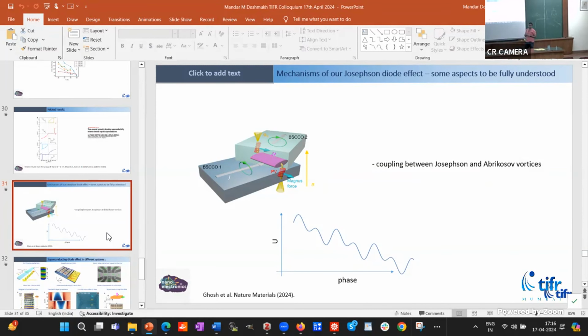Is that a point of inflection on the curve or something like that? This is a local minimum where the system can get trapped. Okay. And the more current you send, the more you tilt it. So either it will switch by thermal activation or quantum mechanical tunneling, whichever the mechanism is. In our case, you don't really need quantum mechanical tunneling at these temperatures, you just need thermal activation.